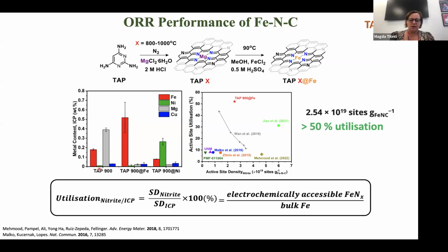And as I said, we have one that doesn't have any iron coordinated, just nitrogen carbon, the one with iron, and the one with nickel. But the one with iron, what was good about this, so this is a comparison with literature. So here you have the active site density, and here you have the active site utilization. Now, the active site utilization is how many of your total number of active sites will be active towards the oxygen reduction reaction. And the way that you determine this is using a technique called nitrite stripping, which gives you the number of electrochemically active sites. And then you divide this over the total number of iron sites that you determine on Mössbauer.